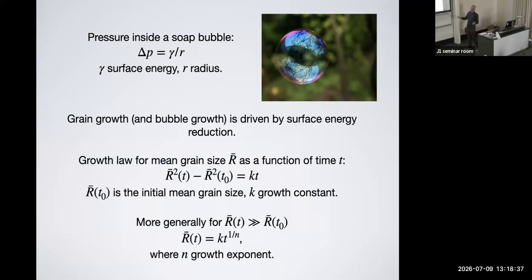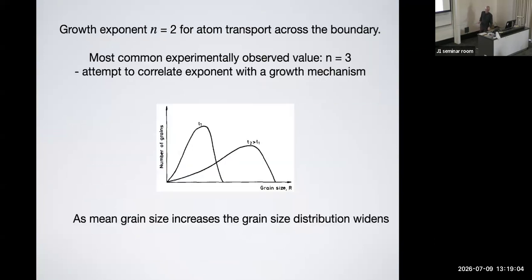What you have to add then, of course, is that this growth constant also includes things like temperature dependence, right? For grain growth in the Earth, it's thermally activated. So you have an activation energy that goes into this grain growth constant. Experimentally, what you do is then determine that growth constant and that exponent. And once you have that, you can calculate grain size for any time. So it looks fairly straightforward, but of course, it's not quite that straightforward. So the earliest model that I showed on the previous slide assumed that you just had atom transport across the grain boundary. And for that particular model where you just take an atom from one grain on one side to the other side, you predict a growth exponent of 2.